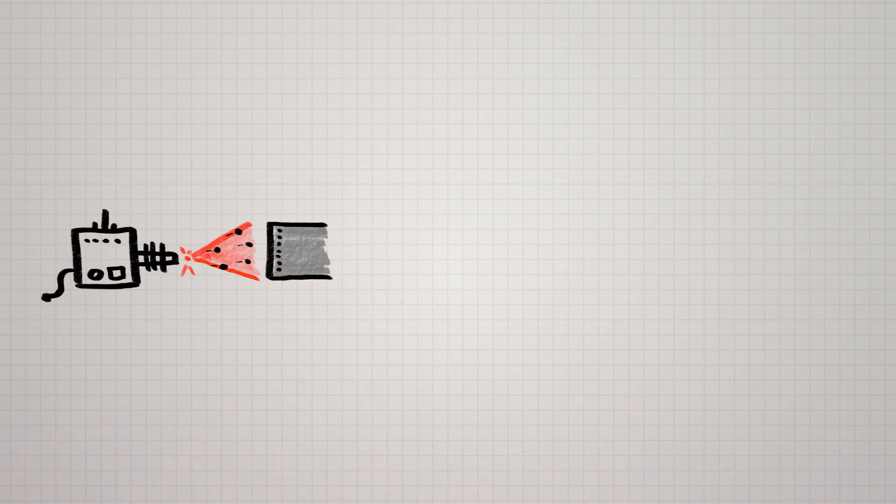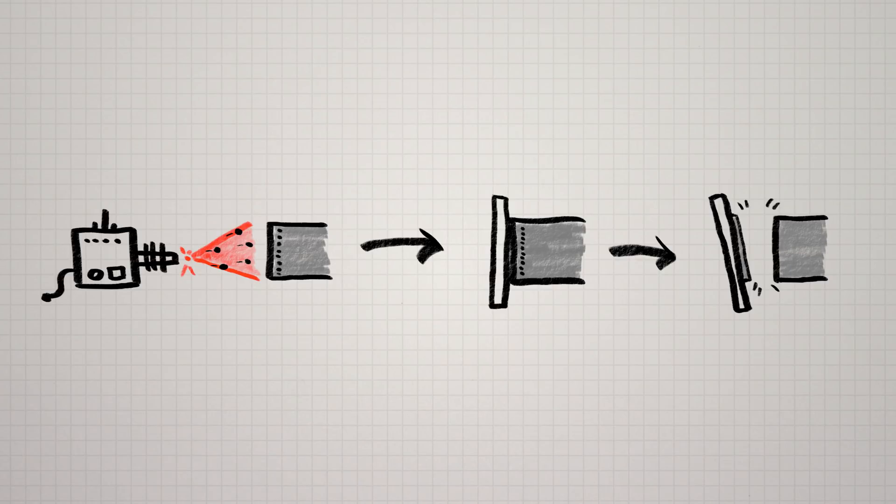So if after the protons are embedded, but before the heating, you glue this proto-wafer onto a piece of glass or plastic, and then heat it up, you end up with a nice thin wafer of silicon attached to a durable and possibly flexible material, with no waste silicon whatsoever. To me, this is really clever physics engineering.